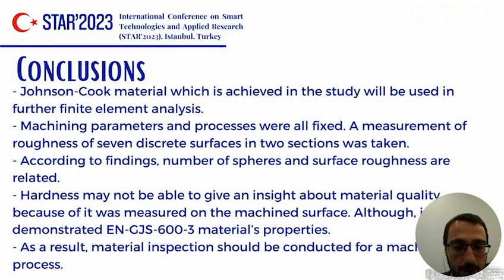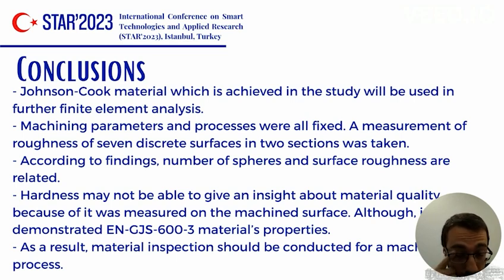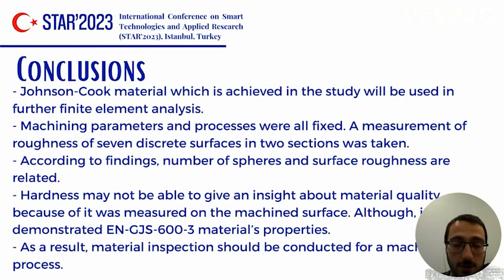In conclusion, the Johnson-Cook material model achieved in this study will be used in further finite element analysis to develop different models. In this study, machining parameters and casting processes were all fixed, and measurements of seven discrete surfaces on two parts were taken into account. According to the findings, number of spheres and surface roughness are related. Hardness may not provide a reliable insight about material quality because it was measured on the machined surface.